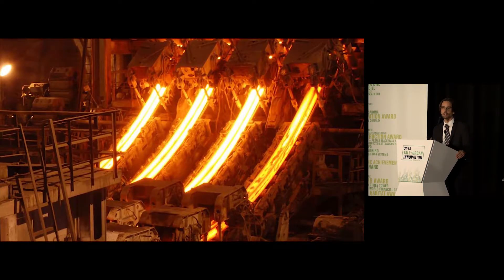We often like to think of structural steel as being a completely isotropic material. Structural engineers think of it as having the same yield strength in all directions, being fully isotropic with the same stiffness in all directions. But that's actually not true. The truth is that the mechanical properties and quality of any structural product — whether it's an I-beam, a plate section, or a casting — are all driven by the manufacturing process itself.